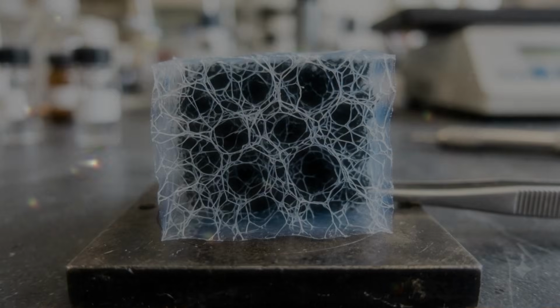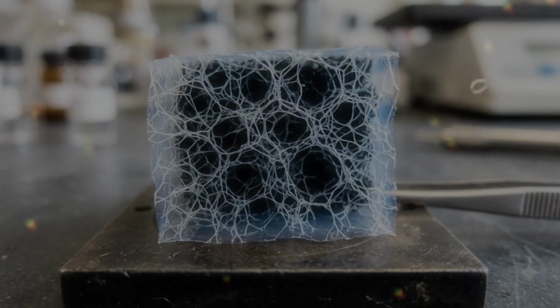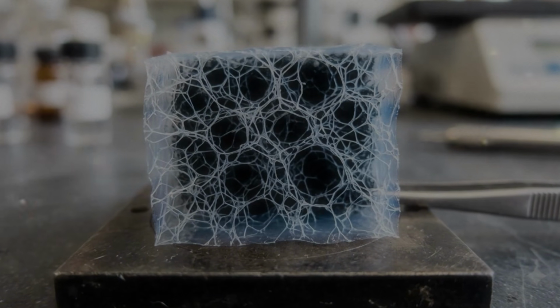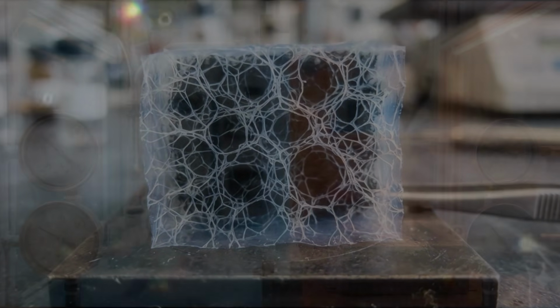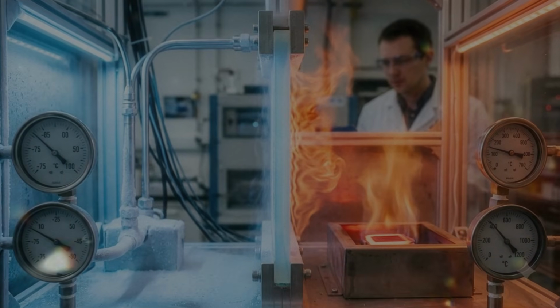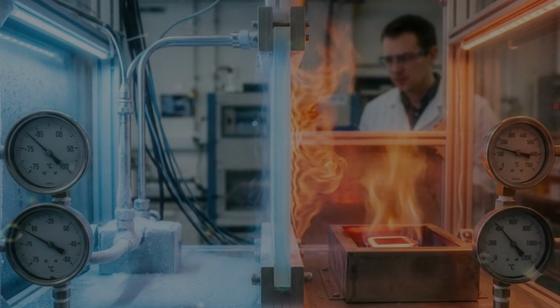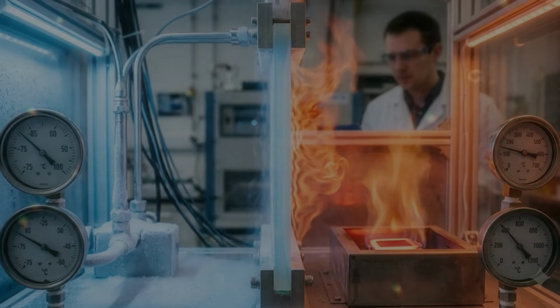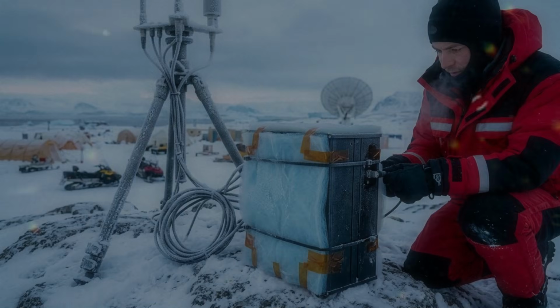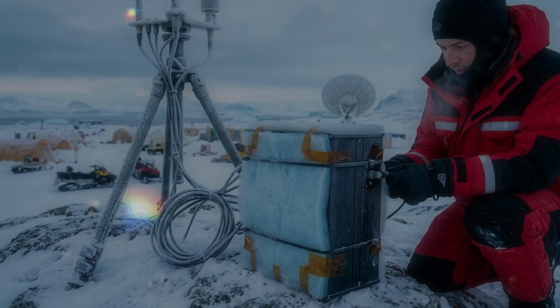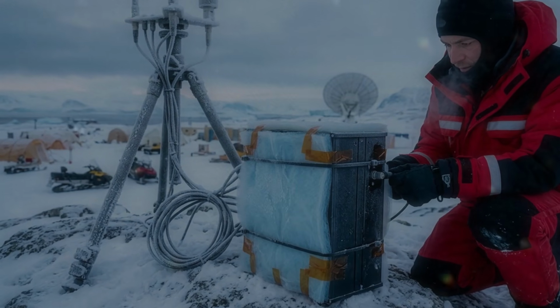This is why producing a large clear silica aerogel panel is much harder than producing a small sample. Every extra centimetre increases the distance that chemicals and solvents must travel. The centre may react differently from the surface. Pressure may not change uniformly. A flaw that would be invisible in a bead can ruin an entire panel.